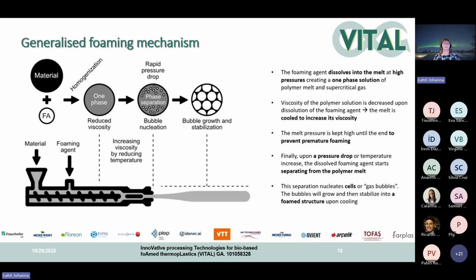Then in the end happens a pressure drop, and then the foaming agent starts to separate from the polymer melt. This separation nucleates the cells or the gas bubbles. The bubbles grow and then stabilize into a foam structure during the cooling process. So the foaming agent is the one that is creating the cell structure and the bubbles.